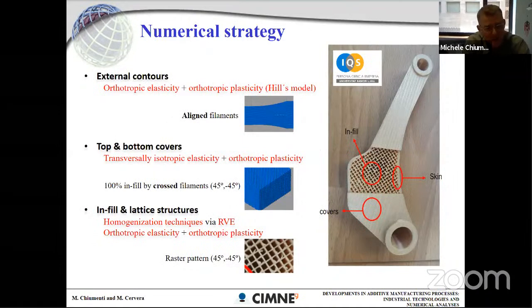Next, we need to define the material data for each one of the zones of the component. As you can see in these figures, during the printing process you typically have three kinds of printing setup. The first one is the skin. Typically, these are completely aligned filaments, which follow the boundary of the component. Then you have what we call covers, typically the bottom and the top covers, which use crossed filaments. It is 100% infill with 45 and minus 45 degree crossing. And finally, you have the infill. This can be just infill like the one you can see here, or it can be done through a lattice structure.